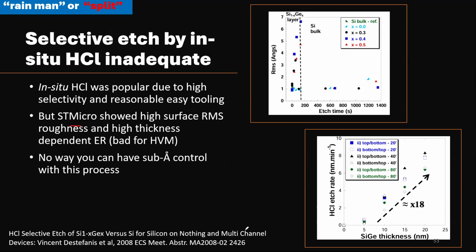I see Michael, I think this paper is very nice. It's showing you that SiGe etch rate has strong dependence on the thickness. The slope is 18. Oh my God. Right, so this is horrible. And then here, look at the etch time. Si1-xGex layer here, such a high roughness. So this process no good. The roughness is like 6, this Angstrom already. 5 Angstrom, no. You need a sub-Angstrom control. Okay, and so this is no good.